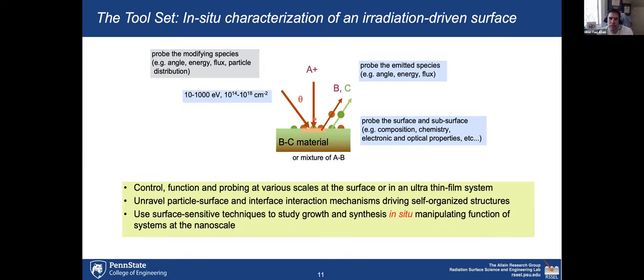The second aspect of the system is that while we're doing the irradiation, we're able in some way to probe that surface. And not only the surface itself, but also what we call the subsurface. That is, we define a surface as the first layer of atoms. The subsurface would be then a few fractions of, let's say, a nanometer or so or below. So the intention is to be able to probe that surface and subsurface to give us the composition, the chemistry, and other parameters as we do the irradiation.